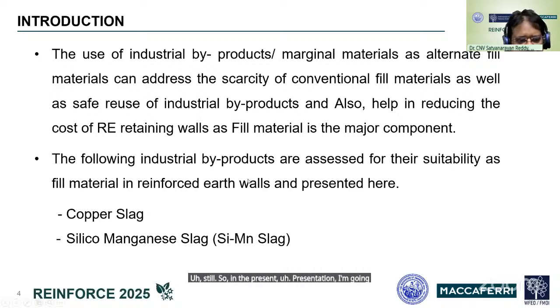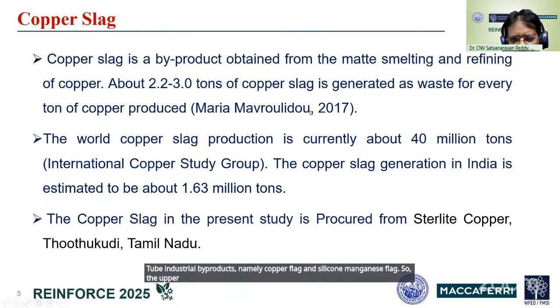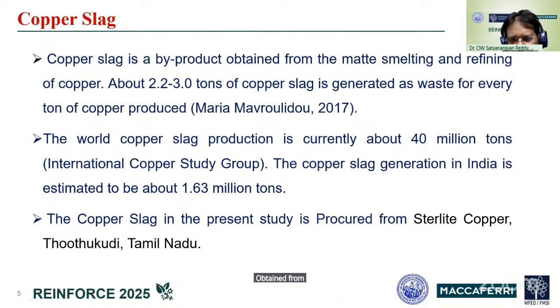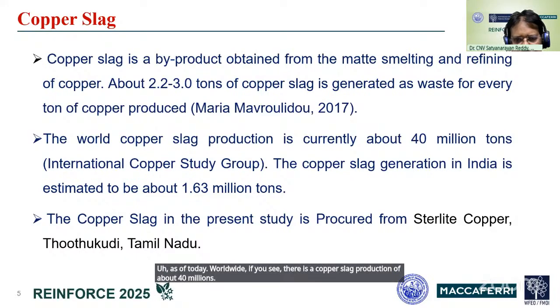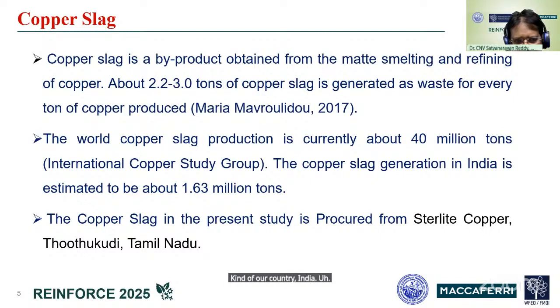So in the present presentation, I am going to cover two industrial byproducts, namely copper slag and silicomanganese slag. So copper slag is a byproduct obtained from matte smelting and refining of copper. About 2.2 to 3 tons of copper slag is generated as waste for every 1 ton of copper produced. And as on today, worldwide, if you see, there is copper slag production of about 40 million tons. And in our country, India, the slag generation is up to 1.63 million tons. The copper slag used in the present study is procured from Sterlite